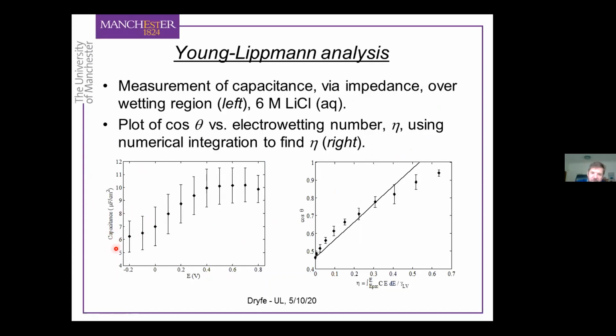We can measure the capacitance of the interface as a function of potential of the graphite electrode. And we can plot from the Young-Lippmann analysis the change in the contact angle, or the cosine of the contact angle, as a function of this parameter called the electro-wetting number, which depends on three things. It depends on the potential you apply, it depends on the capacitance of the interface, which we know from the impedance, and it depends on the surface tension of the water vapor interface. So we put those parameters in, and that gives us a solid line.